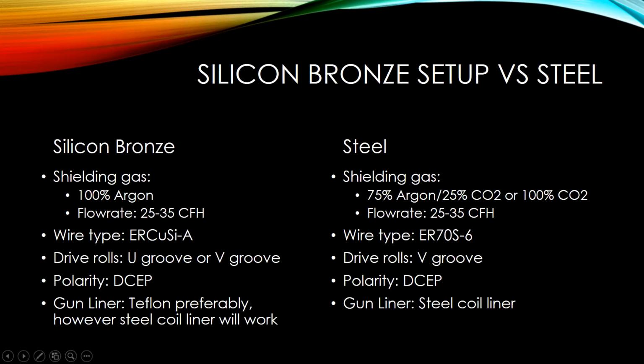So as opposed to a steel setup, if you're welding on mild steel, you'd typically be using a 75% argon, 25% CO2, or 100% CO2 shielding gas. Flow rate of 25 to 35 CFH. Typical steel wire is going to be ER70S-6. Lining that up with a V-groove drive roll, polarity, direct current electrode positive, and typically the kind of liner that you use is steel coil liner.